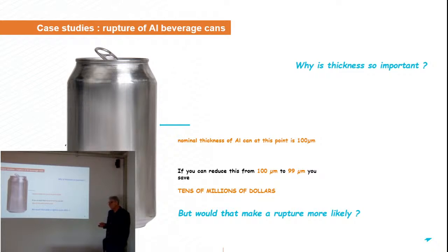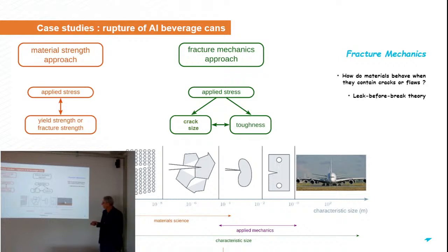But if you reduce the thickness, maybe you can make fracture more likely. So we are here in the case of the fracture mechanics approach, and no more in the material strength approach, where you simply compare the applied stress to the yield strength of the material. In the case of fracture mechanics, you have to consider the applied stress and compare it to the crack size, the size of the possible crack in the material, and the toughness of the material. This is a little bit more complex.